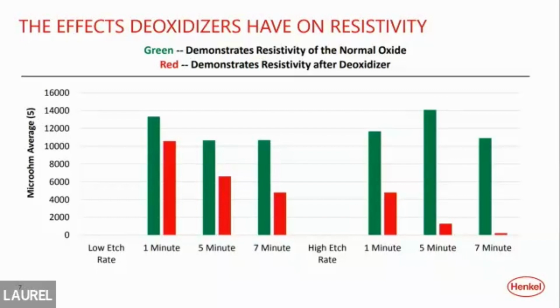But that's tight. And that's with a conversion coating, because as soon as you remove that aluminum oxide coating, aluminum wants to put that oxide layer right back on. So I need to seal up that coating immediately. I need to get it rinsed and get it passivated right away. Because if it hangs out, it's just going to put another aluminum oxide layer right back on. So no line stoppages.